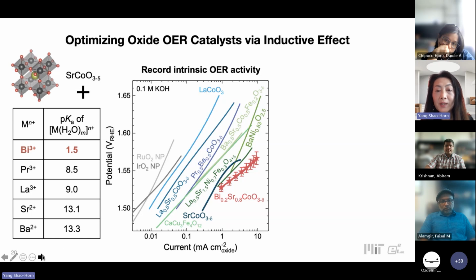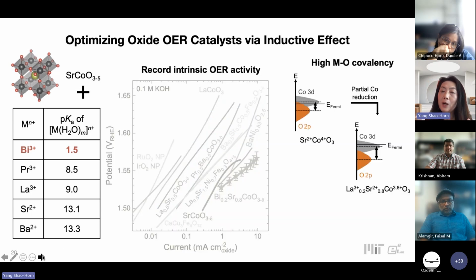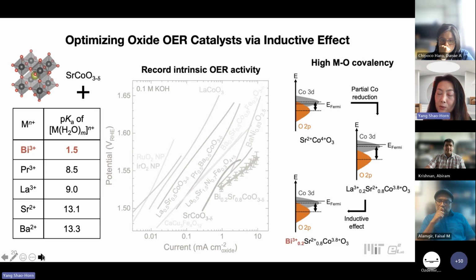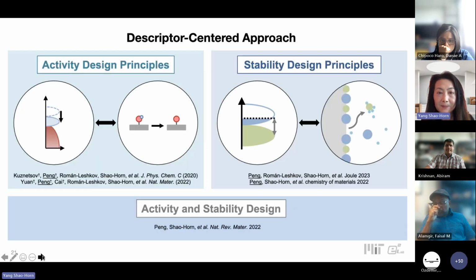And this has to do with fine-tuning of the so-called inductive effect, through A-site tuning of modifying the cobalt-oxygen covalency, and that allows us to tune or optimize the binding of different species in order to oxidize water to generate molecular oxygen. So really it is tuning the decoupling of the D states, the oxygen p band, and the covalency through this inductive tuning by choosing the most acidic A-site ions.